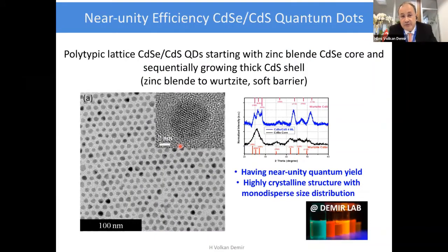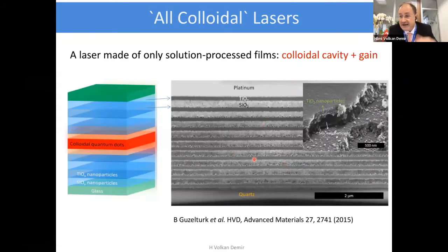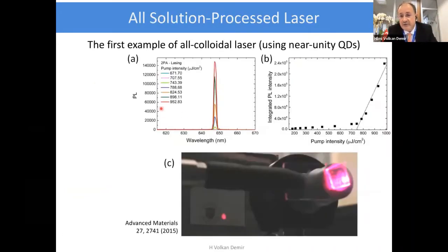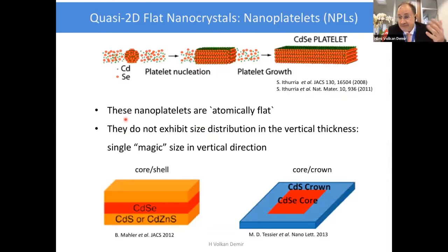With that motivation, we have been developing these very special colloidal quantum dot emitters, and we can have near unity efficiency very routinely, and we can make devices very compact using what we coin all-colloidal lasers. This is basically where the quantum dot material is solution processed, as well as the sandwiching mirror. So everything is very low cost and in principle can be applied to quite large areas and essentially on any surface you desire. With that, we were able to show, at the time, record-breaking performance of these colloidal dots to lase from all solution-based processing. Of course, with that, we can achieve only a certain level of performance, and for us to push the limits is critical.